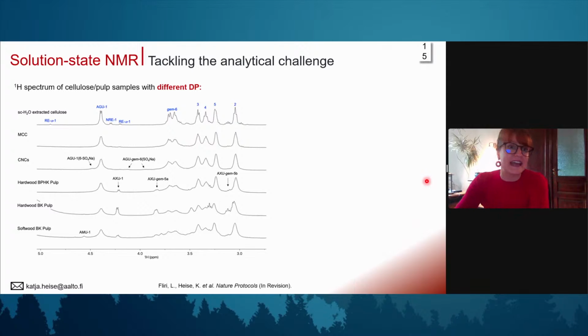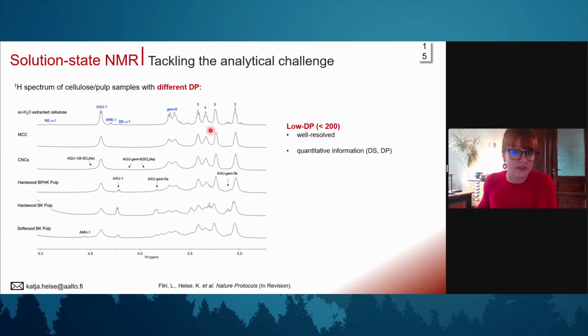Then I mentioned that we now use it for cellulose nanocrystals. We have very nice spectra for microcrystalline cellulose, but you can also use this method for pulps, so for high molecular weight samples. For the low molecular weight or low DP samples, the spectra are well resolved. So these are the three ones here on the top. You get quantitative information. You can calculate a degree of substitution after modification, and also DP values.